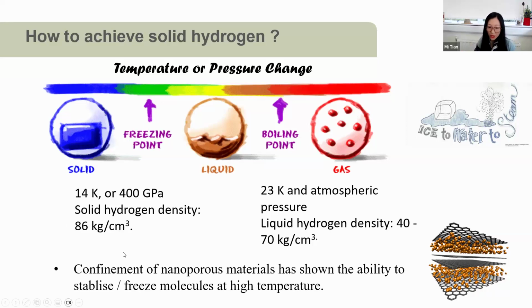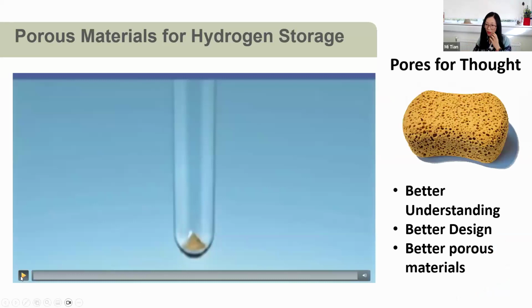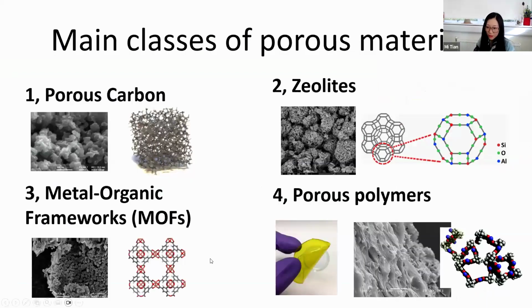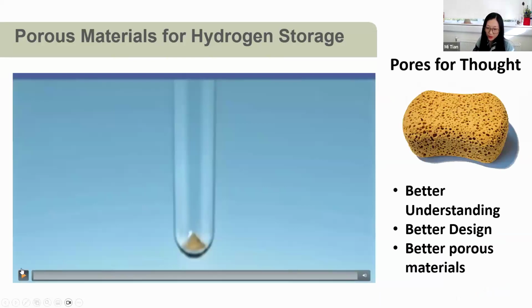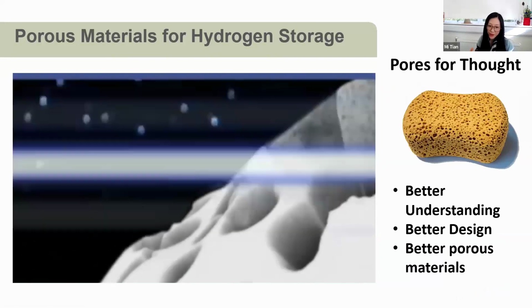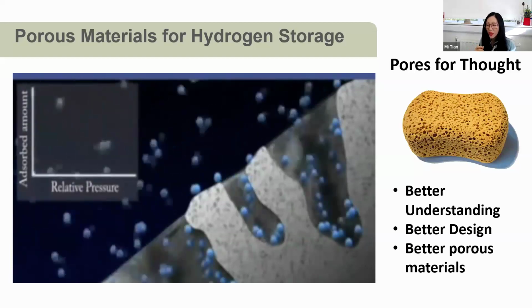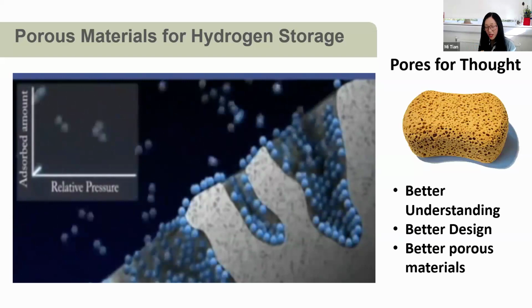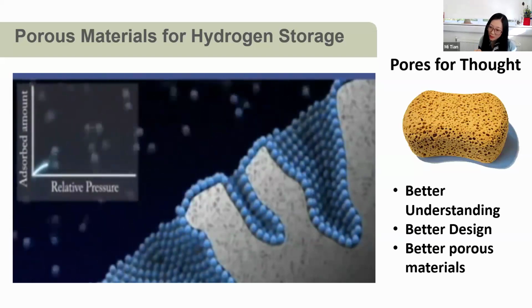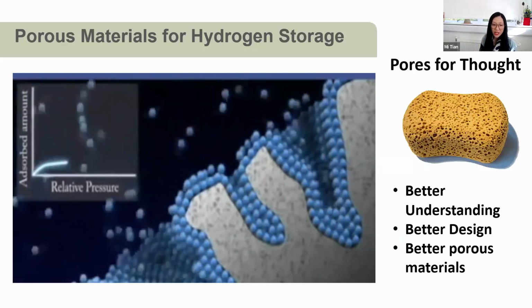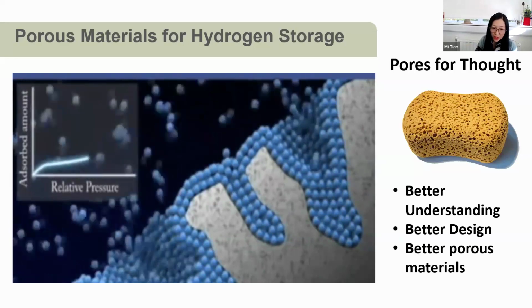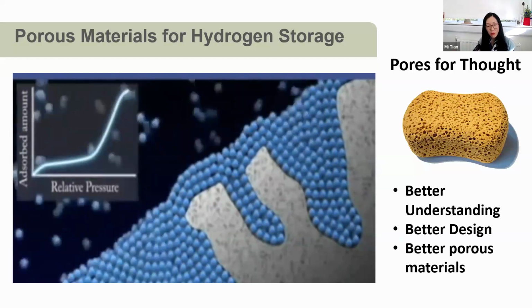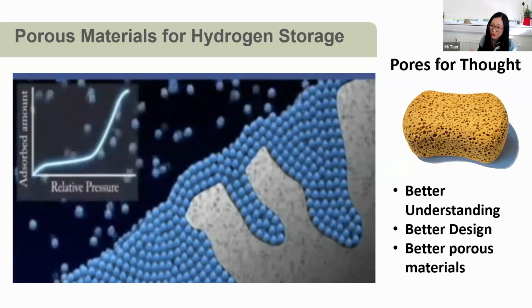And then we found that nanoporous materials have shown the ability to stabilize, to freeze the hydrogen molecules at a much milder condition. The very special feature that porous materials offer is a large surface area and very tiny pores. As soon as we expose this clean porous surface to gas, this tiny space will absorb, compress, and store gas molecules. So we call these nanoporous materials a molecular sponge. Like a sponge absorbs water, our novel molecular sponge can absorb hydrogen.